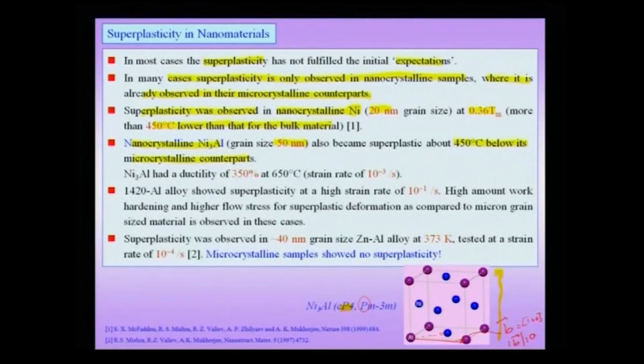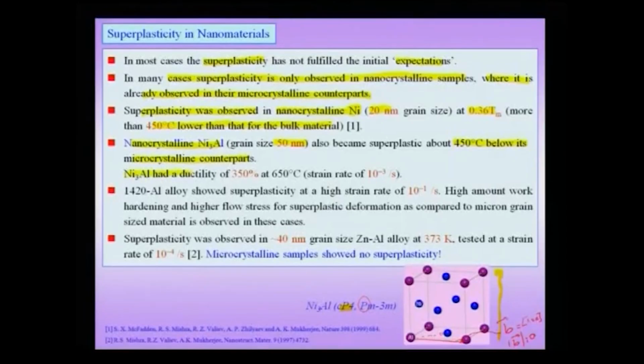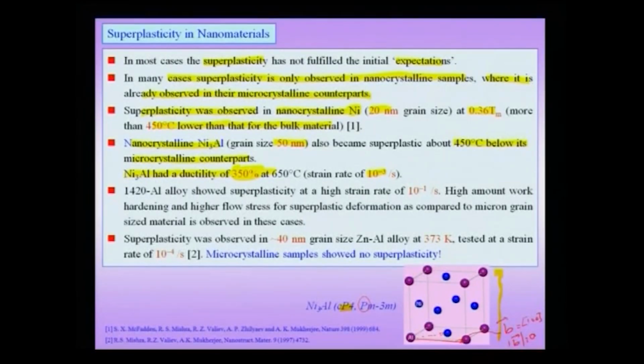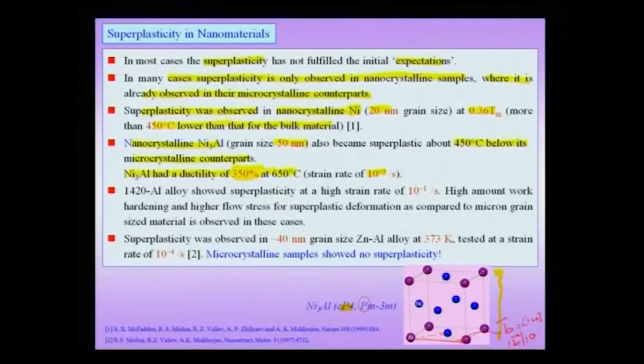Ni3Al is a technologically important intermetallic, and therefore, if I am able to superplastically form Ni3Al 450 degrees below its microcrystalline counterparts, then I have very important industrial applications for the nanocrystalline sample. Ni3Al had a ductility of 350% at 650 degrees at a strain rate of about 10 power minus 3 per second. So, here again we are not talking about very high strain rates of deformation, reasonably slow strain rates, but nevertheless we have a good ductility of 350%, and given the fact that this intermetallic tested in tension would normally have very negligible ductility, this is very good, and you can see the temperature is also very reasonable for an industrial application.